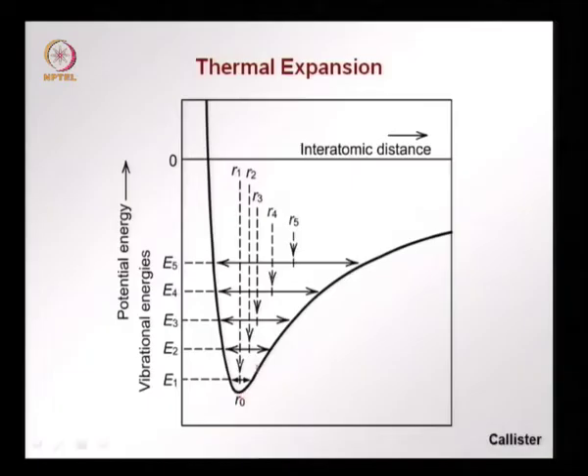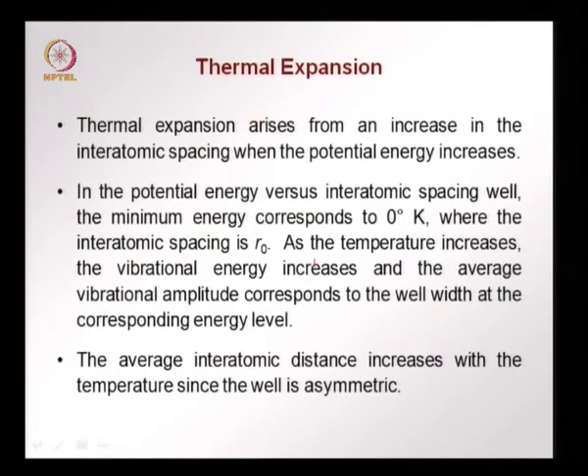Since this well is not symmetric, but is shaped like this, the mean distance at any energy now deviates to the right. Okay. So, we have a deviation of the mean distances at any energy. As the mean now deviates from R0, the material experiences expansion. This is the expansion that we observe in the material at different temperatures due to the vibration that is occurring in the interatomic distance. So, thermal expansion arises due to the increase in the interatomic spacing as the potential energy increases.